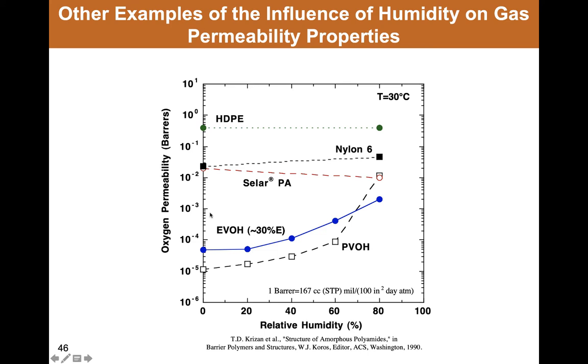This last case is of particular interest because polyvinyl alcohol is a dominant barrier material in high barrier packaging for things like ketchup bottles, and in other cases when packaging highly oxygen sensitive products. Polyvinyl alcohol can't be melt processed the way many packaging materials can, and so it's often copolymerized with ethylene to make it melt processable. And so very typically in high barrier applications, a thin layer of ethylene vinyl alcohol copolymer is used.